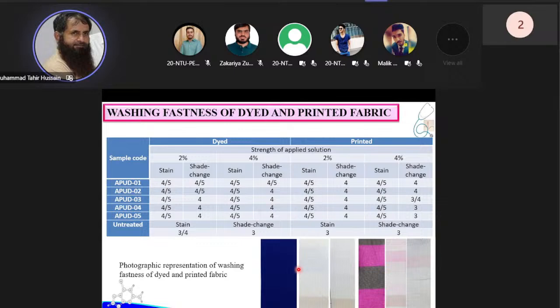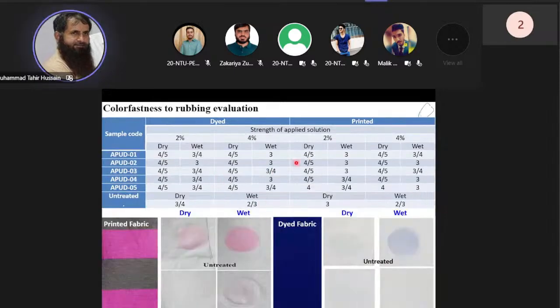We also studied the washing fastness of the dyed and printed fabric, and we observed that fewer stains appeared on the multi-shaded fabric using a small concentration. With increasing concentration of the finish, the washing fastness decreased. We also determined the color fastness to rubbing using dyed and printed fabric, and we found the same observation here, that the smaller concentration of materials showed good fastness properties as compared to the material that contains the highest concentration of curcumin and the chitosan.